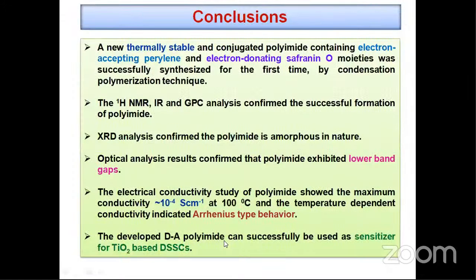Now conclusion. Here, a new thermally stable conjugated polyimide containing electron accepting perylene and electron donating safranin O was successfully synthesized for the first time by condensation polymerization technique. The 1H NMR, IR and GPC analysis confirmed the formation of the polymer. The synthesized polymer has high thermal stability, low band gap, and shows good absorption properties.